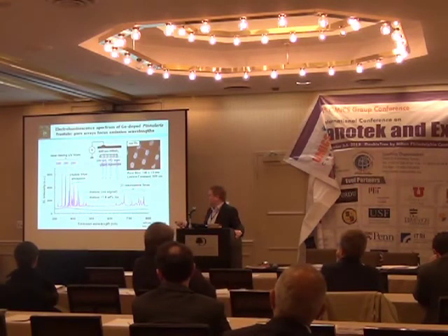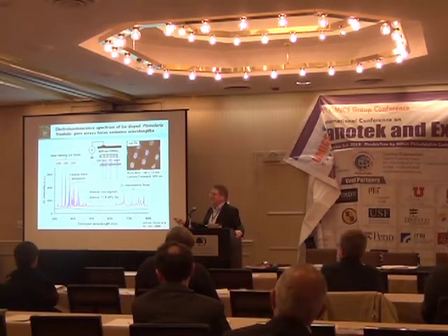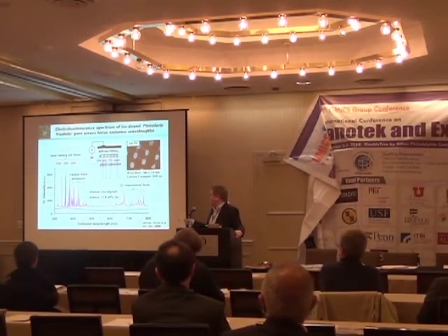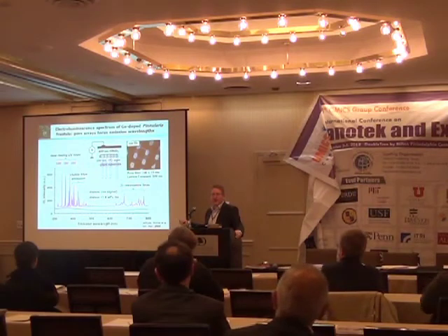If you just look at it with the naked eye, it looks kind of blue from electroluminescence charging. But if you look at the full spectrum, you see some interesting things. The first thing that you see is a series of near lasing lines in the UV. And then complementary to those are the 2 lambda resonance lines associated with those primary emissions.